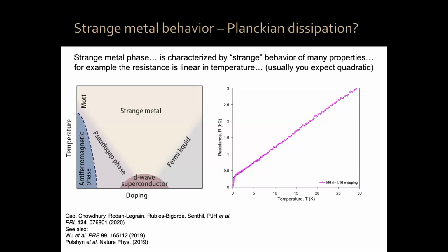Depending on whether you use the 2 pi or not in the Mott-Ioffe-Regel limit, we have already gone well past it in some of our devices, but we're still within a small factor of it. Because we can do these maps as a function of density, we know that as we fill closer to the band edge, it gets more easily excited into those regions. So we can see how proximity to the band insulator is giving you transport at high temperature, and the resistance bends down more quickly. So it has an obvious interpretation.